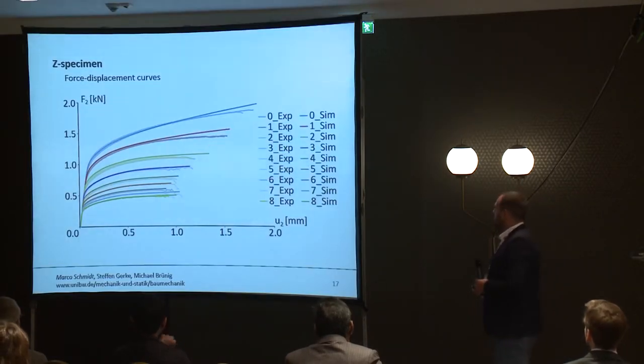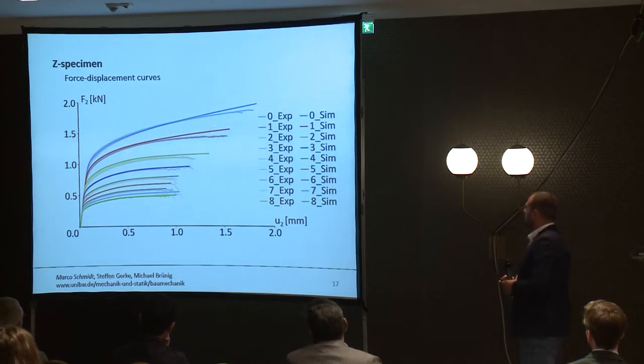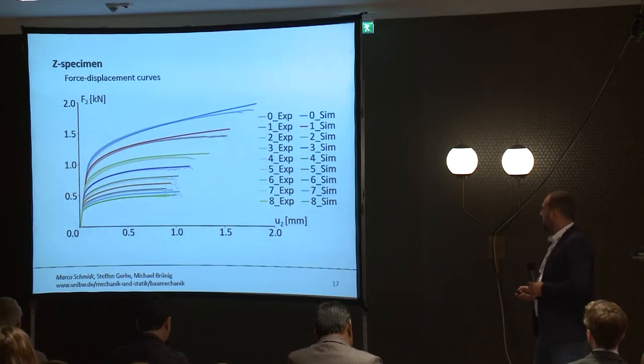Here, you can see the force-displacement curves of all experiments and numerical simulations in shear direction. You can see that there is a very good agreement between experiments and numerical simulations for all load cases. You can also see that with increasing compression, less forces were achieved and the specimens failed with smaller displacements.